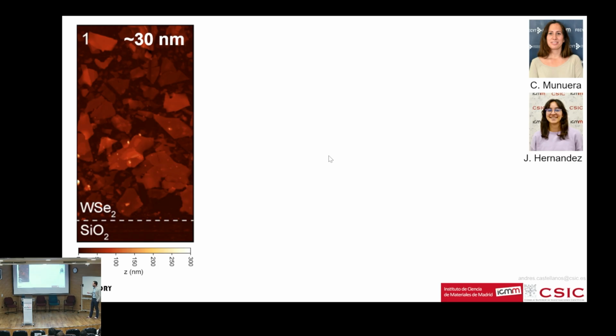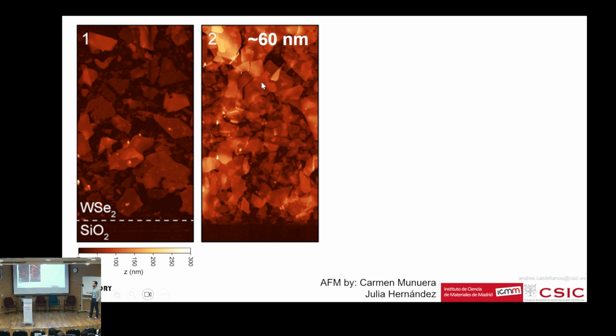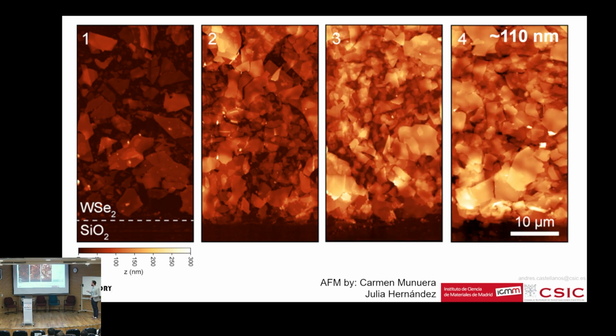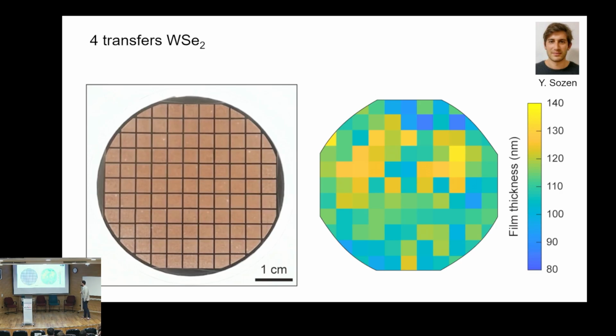So you start with 1 transfer where the average thickness of the film is around 30 nanometers. Then you do 2 transfers, and you get around 60, then 90. When we did 4 transfers, it was 110. Within the experimental error, it's kind of adding up. So you really can do this sequentially, making your film thicker and thicker. And remember, for applications, thicker films in the order of tens of nanometers are more interesting than a single layer of molybdenum disulfide or graphene or anything, because they are more robust against mechanical deformations, environmental conditions and so on. So the films are rather homogeneous over wafer scale, right?